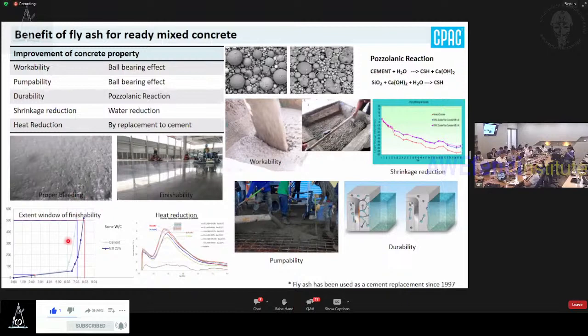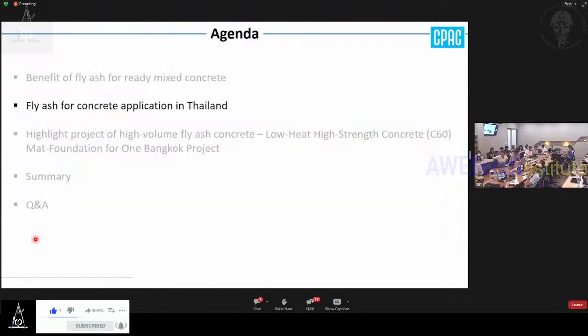And also, recently we have research about floors that require troweling, because after construction is finished, this floor is going to face wear resistance demands, because a lot of forklifts will move on the surface. So troweling is very important for this kind of floor. And we found that fly ash can extend the finishability window when you trowel. That means you can finish for quite a long time and you can make a really flat floor. That is the effect of fly ash that we found right now. So this is overall the benefit of fly ash.